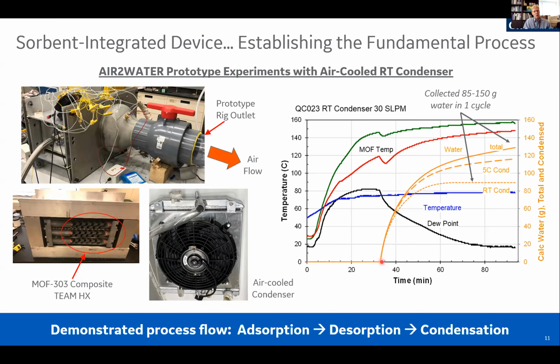And so you can see here is the water. We open up that port with a little bit of sweep gas. It drives off the water. And depending on the temperature at which we condense it, we'll get different amounts of water. There's about 400 to 500 grams of the sorbent that is embedded in these reactors. And Omar showed you one material that had about 40% uptake. So that gives you roughly 160 to 200 grams of water that's in there. And depending on how we run the system, we can get almost all of that water out.